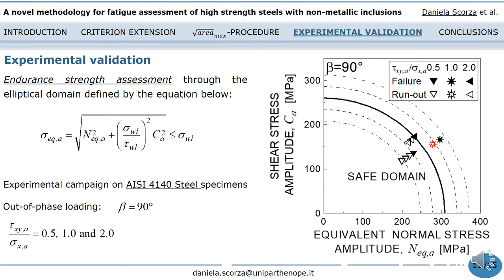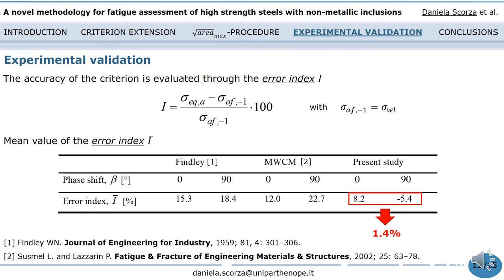For the out-of-phase multi-axial loading conditions, the estimations are in agreement with the experimental data, with the exception of one point for the loading condition with shear to normal stress amplitude ratio equal to 0.5. The accuracy of the criterion is evaluated through an error index, whose mean value is equal to 1.4% for all loading conditions examined. A comparison is performed by applying the Findley criterion and the modified Wöhler curve method, and a more satisfactory accuracy is obtained by applying the present study, with the error index mean value lower than 10% for both in- and out-of-phase loading conditions.